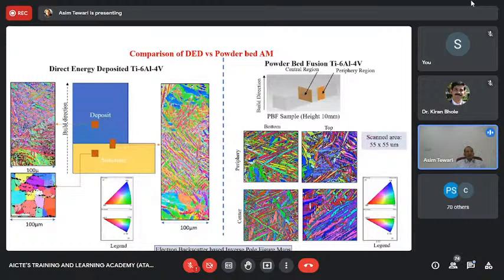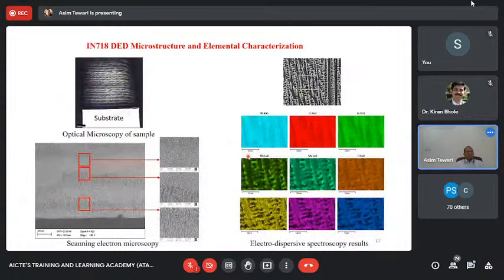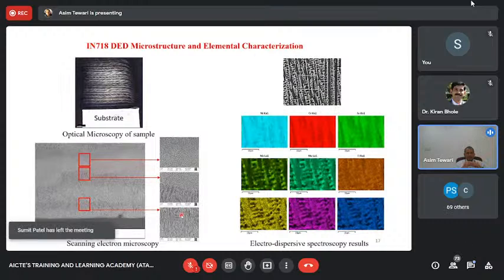Now, once you see this, you can, of course, take the same thing to more complex cases of Inconel, which is another very big area which we focus on. What you see is that there are specific signatures of layer change. So this is the first layer, this is the second layer, this is the third layer. As you go, you see these lines. These lines show that a change in layer is happening, and that is happening because the rate of cooling for the top of that layer and the bottom of that layer is different.